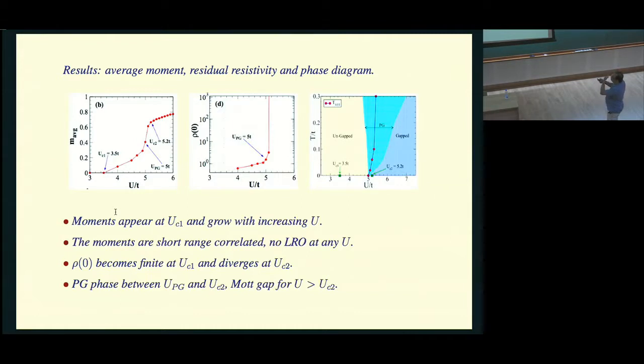And in fact, the resistivity, when you compute it, is 0 below a certain value, below this UC1, and then increases in a certain manner and blows up when you go to some value called UC2. At some large enough value of the magnetic moment, a Mott gap shows up in the spectrum. Because of the vanishing density of states, the resistivity goes to infinity. And this is the picture of the Mott transition. So somewhere here the Mott transition occurs.